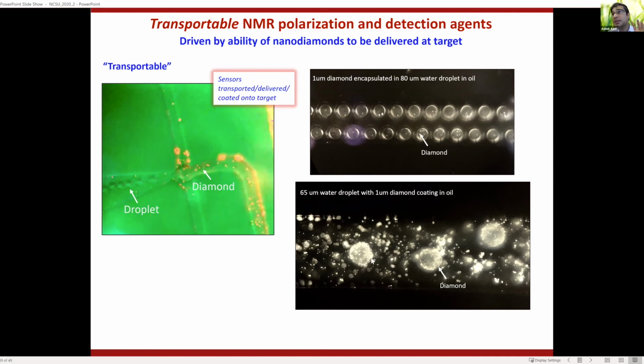And in this regime here, we've got nanoparticles of diamond that are dressing the droplet, and we want to use it as a means by which we can polarize materials inside the droplet, as well as study the surface of the droplet itself. In this configuration, when you shine light, the particles see all the light, and the material inside could be opaque, there's no problem. And the polarization can then be funneled from the outside, from these droplets, to the inside. It also allows you to study many interesting things about droplets themselves, including reaction acceleration in droplets.